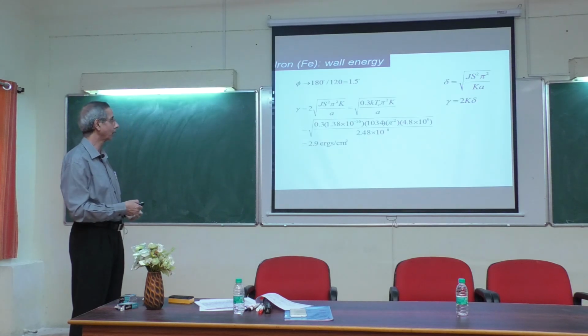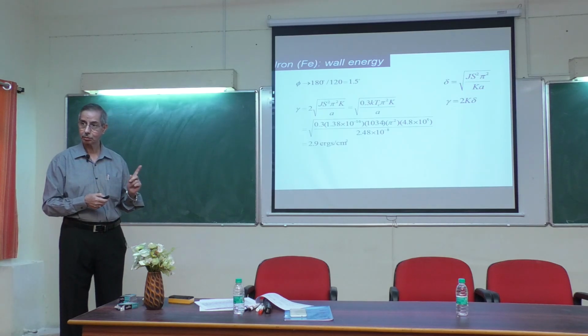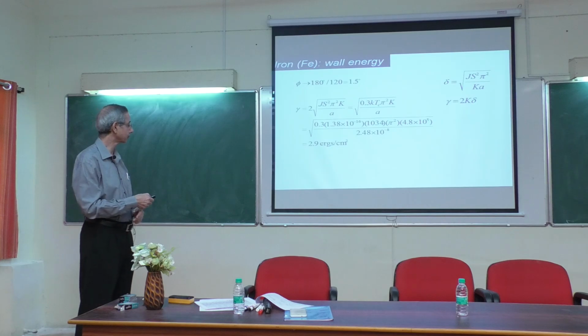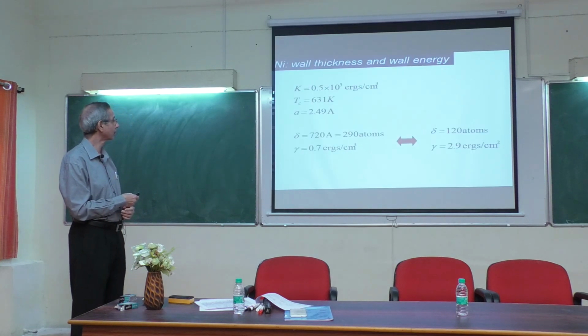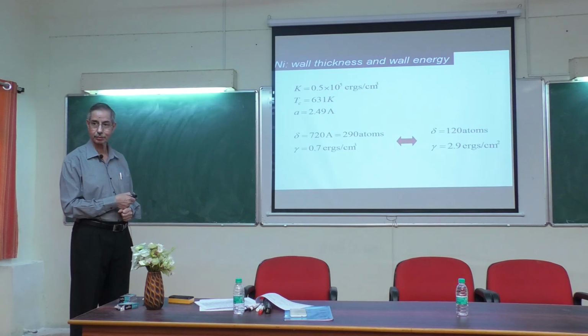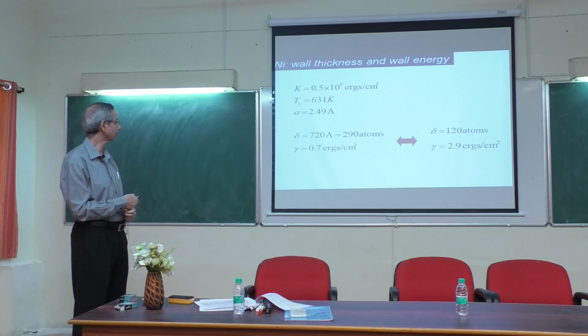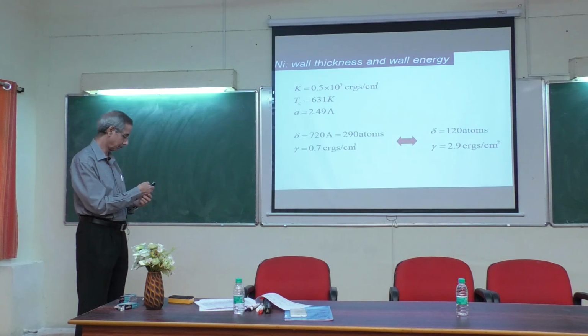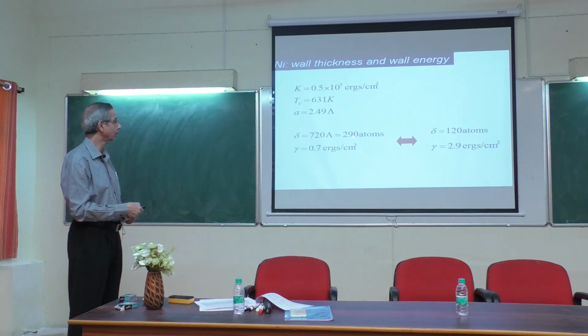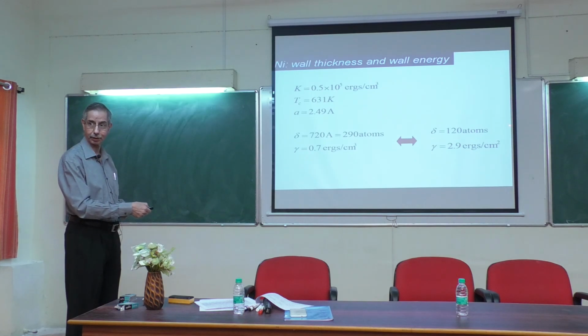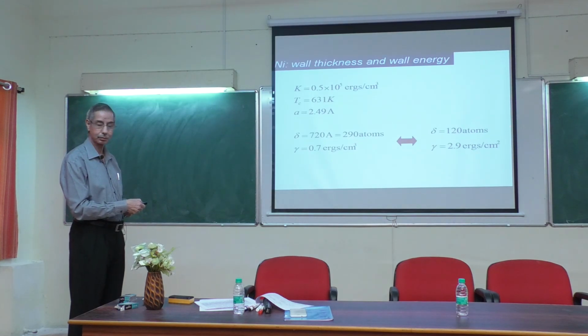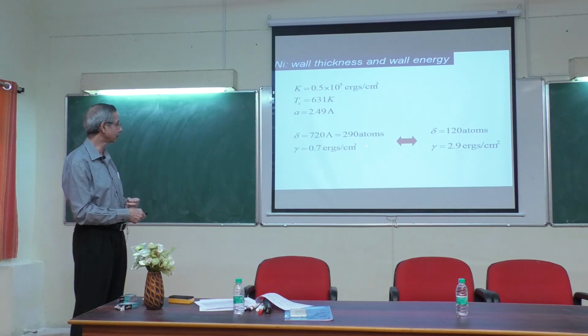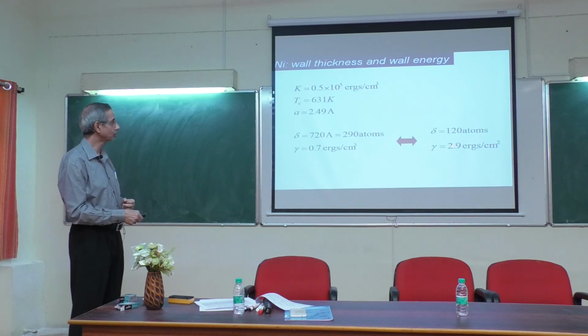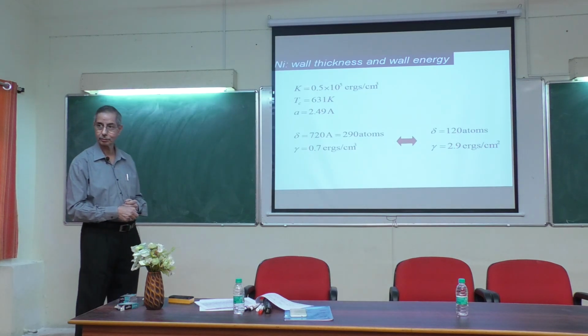Domain wall energy, you calculate the same way. You will get something like 2.9 ergs per centimeter square, because it is domain wall energy per unit area. Gammas are like that. Now let's go to nickel. You see here the anisotropy has reduced by one factor, and Tc is lower, of course. A is comparable, it's not so different, but then this delta is 290 atoms from 120 in iron. Iron was 120, nickel is 290. And this wall energy is now 0.7 ergs per centimeter square. Compared to 2.9, that is roughly 4 times smaller. Right?